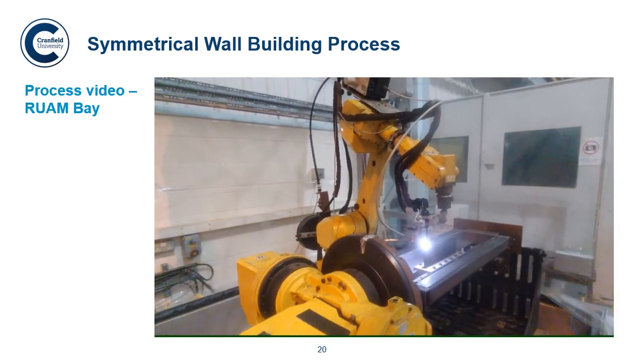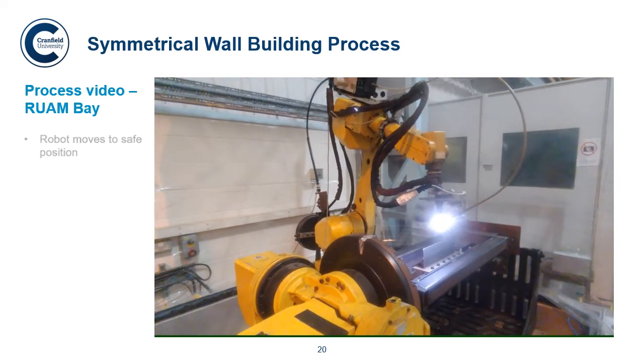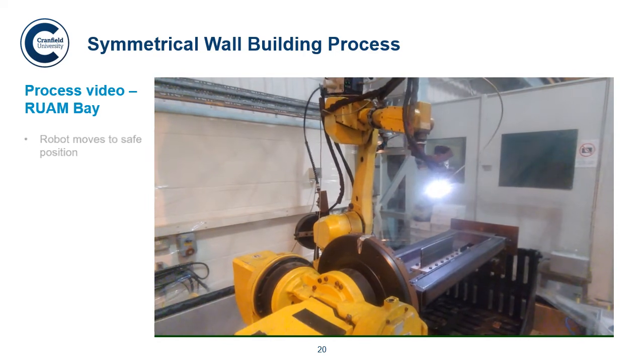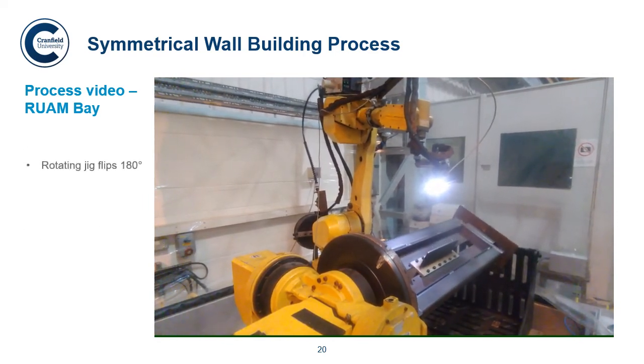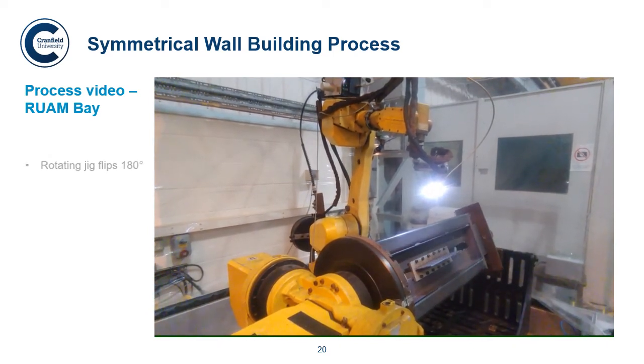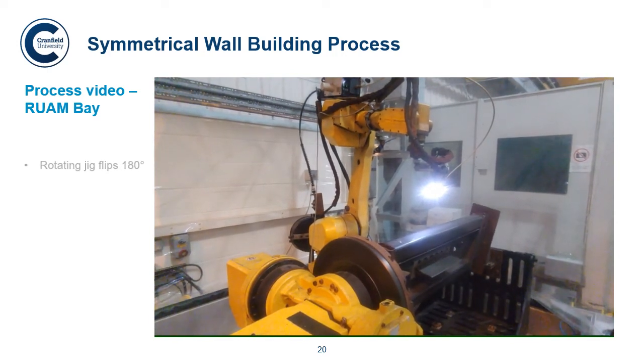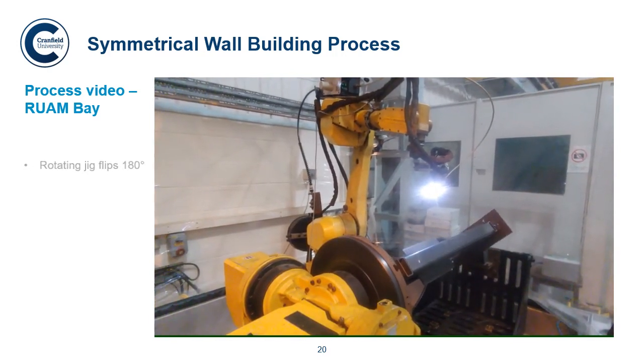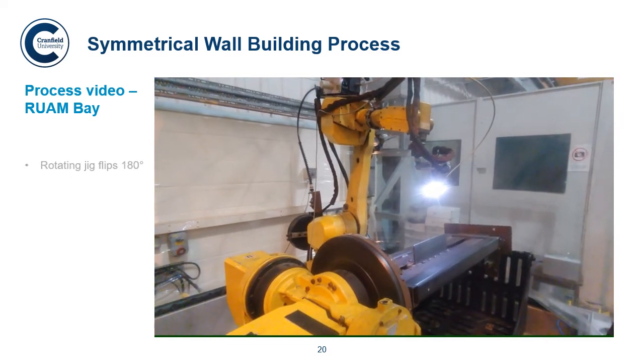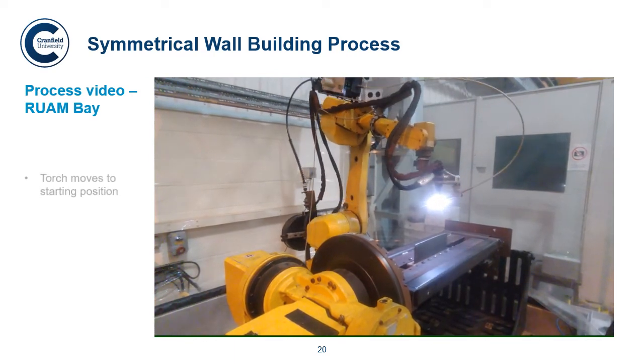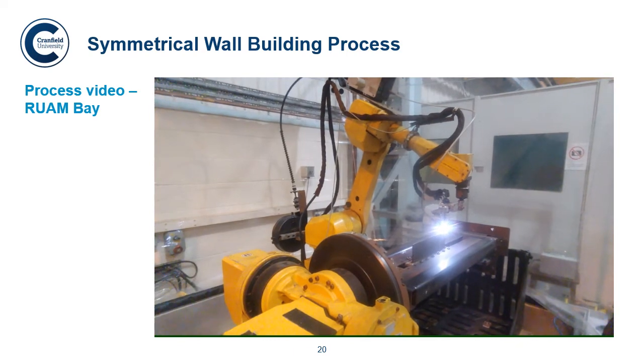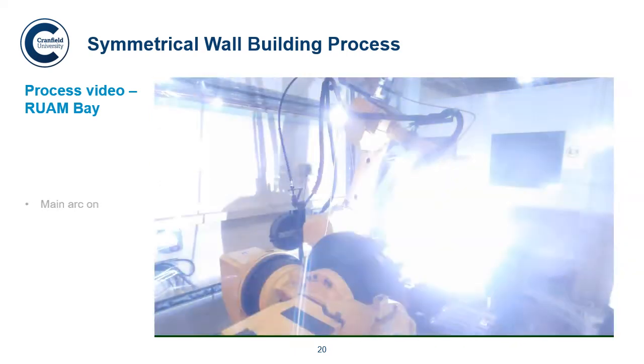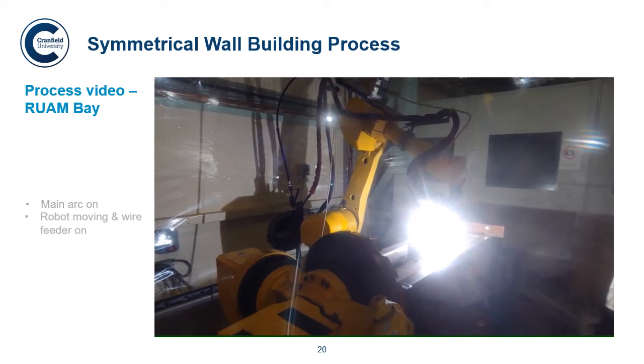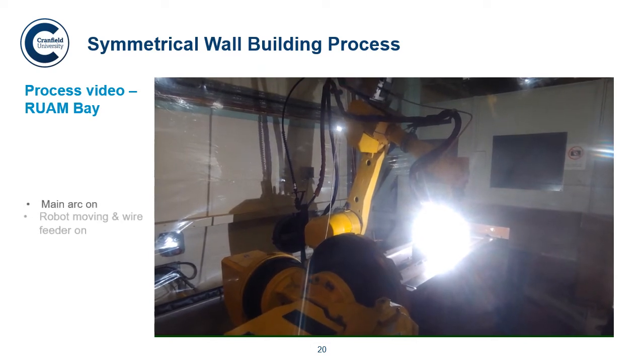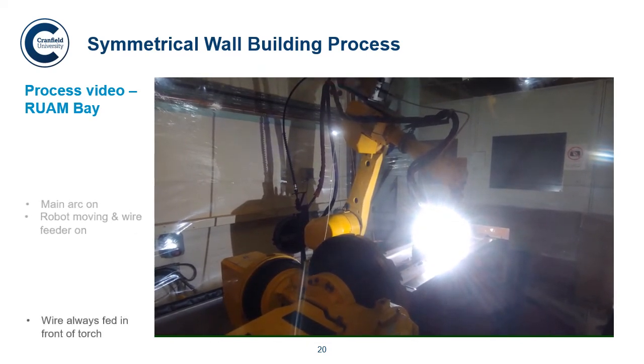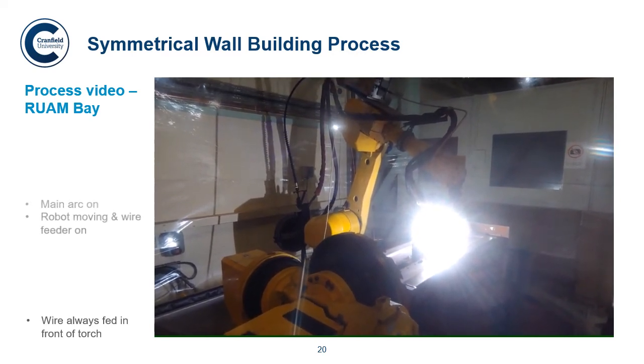So here's a quick video of the process that I used. The robot is going to move up to allow the part rotator to rotate through 180 degrees for us to get to the other side of the substrate. And when we get to the other side of the substrate, the robot is going to come back down. It's going to turn around and go down to the starting position, and the main arc is going to come on, and the wire will start feeding. As it's moving along the substrate, it's going to be feeding wire and depositing that to form your part. The wire is always fed in front of the torch as well.